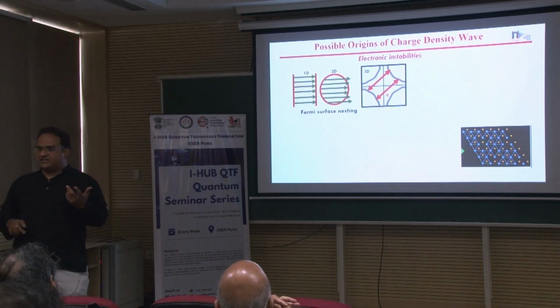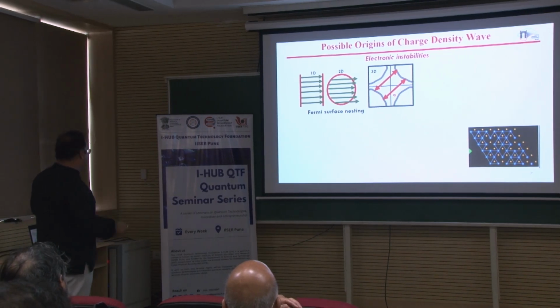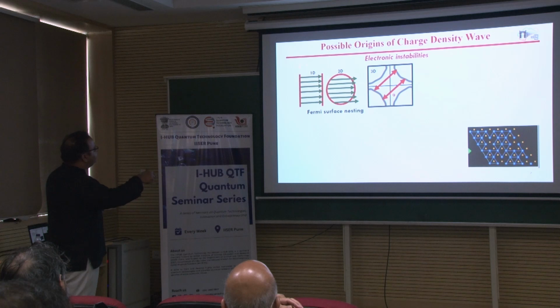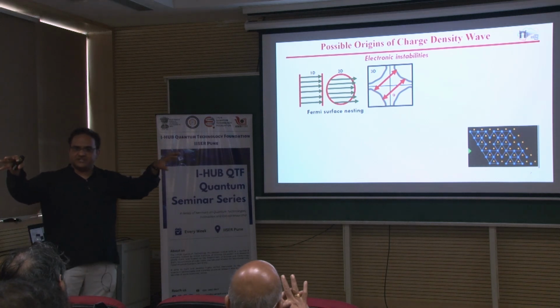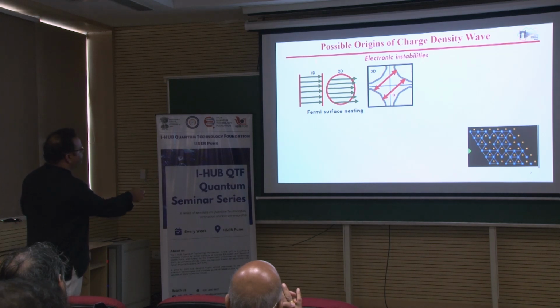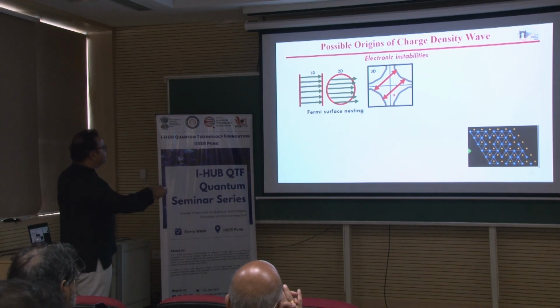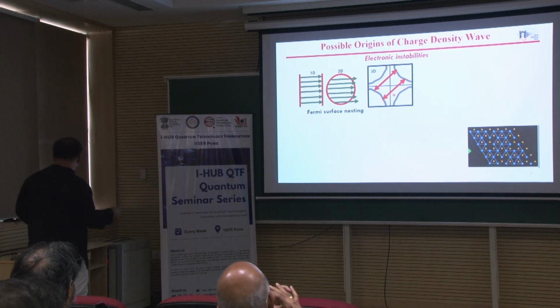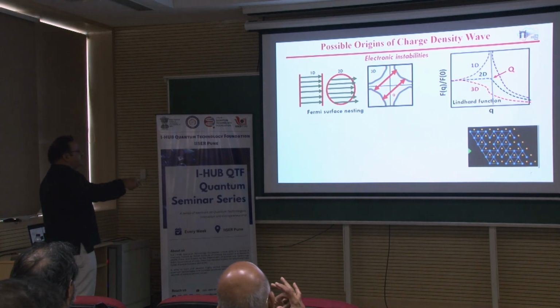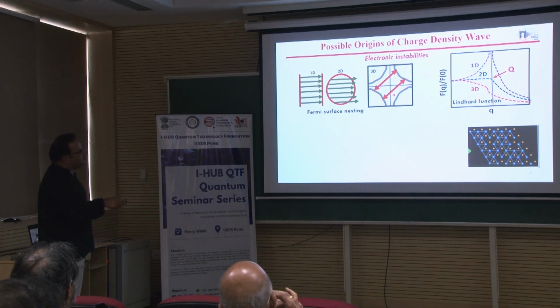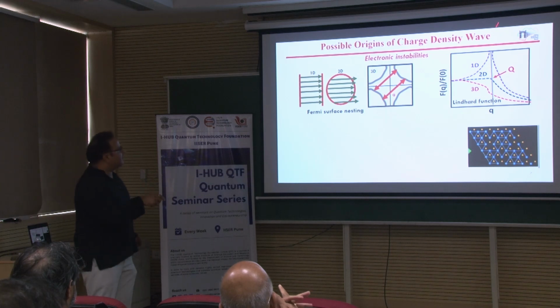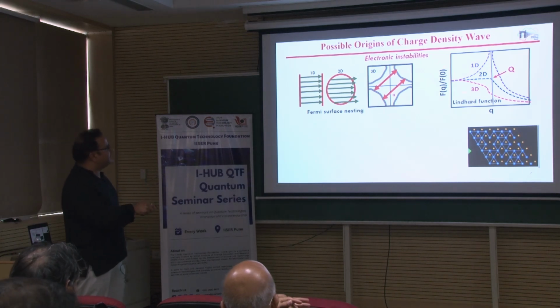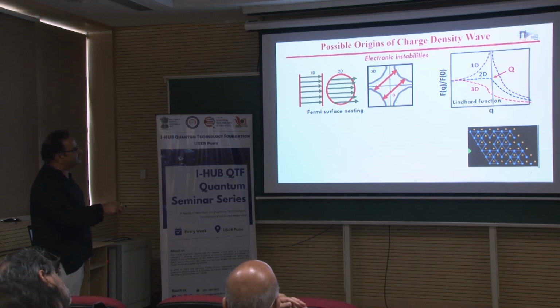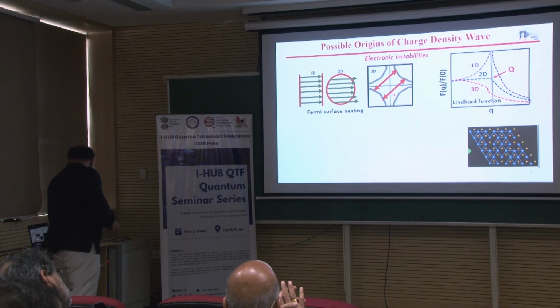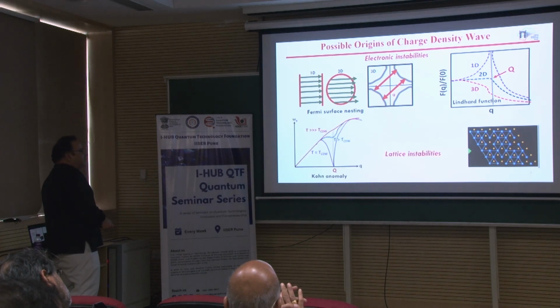What are the possible origins of the charge density wave? In the literature, one of the possibilities is the Fermi surface nesting. So, in one dimension, you consider this red one as the 2 Fermi surfaces of the 2 atoms here, and they are connected by the wave vector here, and these are the connecting vectors. So, this is a one dimension charge density wave. In 2 dimensions and higher dimensions, it is more complicated because the q vector does not lie in the Brillouin zone. So, Fermi surface nesting is one, and this particular part also gives rise to the instability in the electronic susceptibility. So, this is the Lindhard function, and it shows 1 dimension, 2 dimension, 3 dimension. So, the charge density wave is very complicated here, and the important aspect is the q vector here. I will tell you what this q vector is.